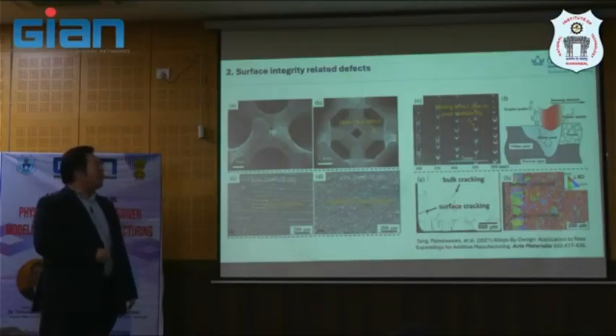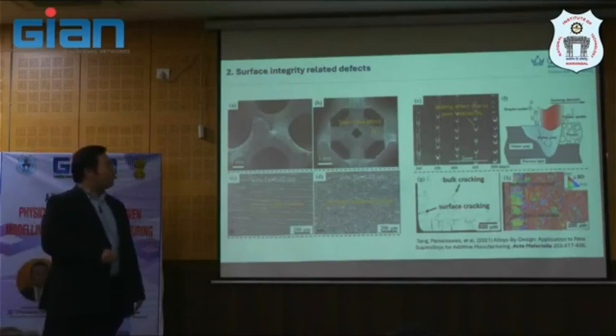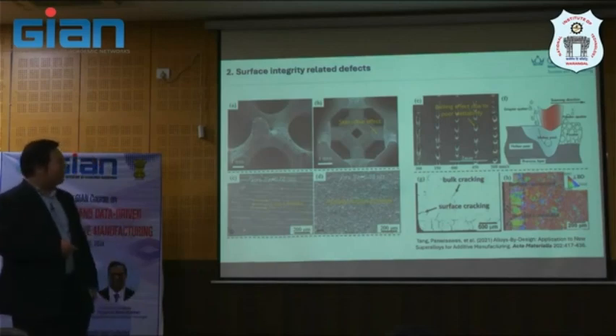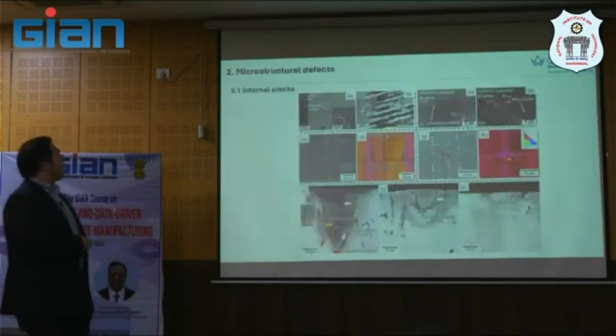But I think the point here that I will show later is actually related to the composition of the material, that probably is related to this effect as well. So there will be a surface cracking that connects the bulk and the surface, and you will see the microstructure in the middle and at the edge are different, looking like this is actually faster, or the growth rate here is more epitaxial or columnar grain, which we will talk a little bit more about later. So this is surface integrity defect.